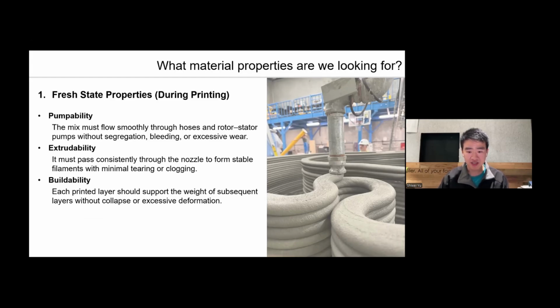The second property is extrudability. The material must pass constantly through the nozzle and form a stable filament without tearing or clogging. And the third is buildability. Each printed layer has to be strong enough to support the weight of the layer above it. This part is interesting because on bigger projects, the lag time between each layer can be very long, up to 20 minutes. By then, the first layer has already gained some strength to support the upper layer. So for bigger projects, maybe it's easier to control buildability because we have more lag time.